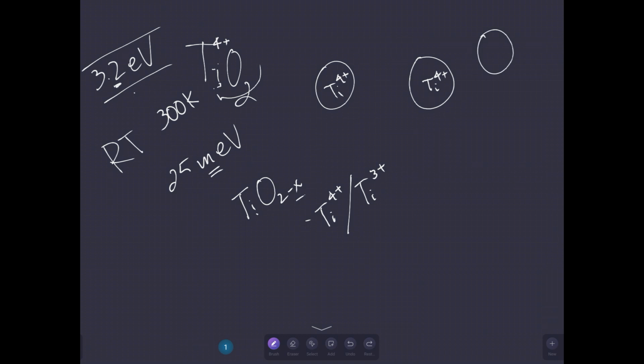Electron hopping between the titanium 4+ and the titanium 3+. If you look locally at the bond, where you have titanium 4+ sitting here and titanium 3+ sitting here, when an electron hops, this one becomes titanium 4+ and this one becomes titanium 3+. So locally, if you think about it in terms of thermodynamics, the change in Gibbs energy is not going to be much - locally, it's still a bond of titanium 3+ in the neighborhood of titanium 4+. So electron hopping now becomes energetically very, very possible.